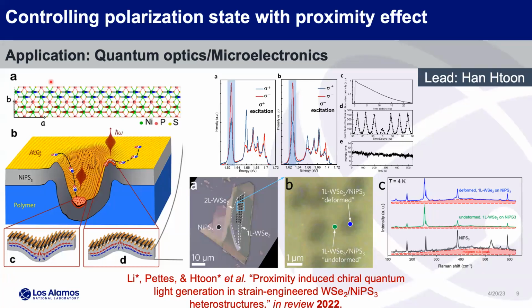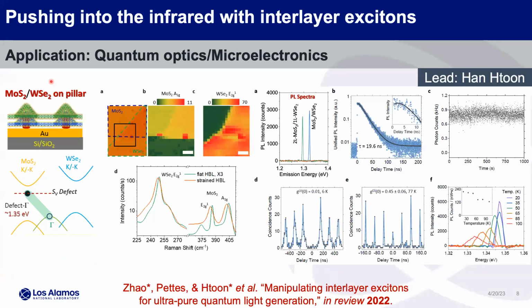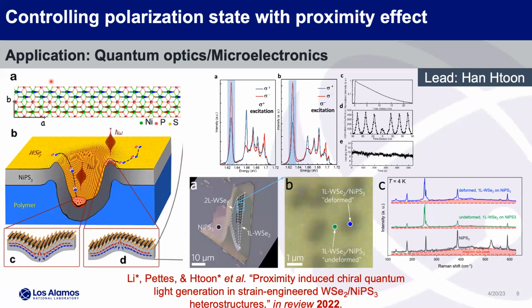In this previous work, I think this one I cut out the magnetism, but we saw small shifts when we were doing things at 8 Tesla. So it wasn't great. There were shifts, there was Zeeman splitting, but you can get much higher effective fields if you put it directly on a magnet. So we're using a 2D magnet. We got it from some collaborators. You'll notice a theme. If we can't do it ourselves, we collaborate. And we got this from some of our collaborators.